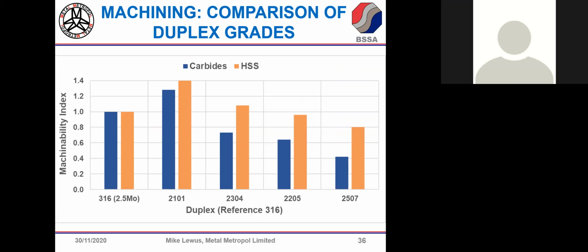More data on duplex, and pointing to the fact that we don't necessarily just have to stick with cemented carbides, which are probably the most widely used cutting tools. High-speed steel cutting tools are still used, particularly for intermittent cutting, and for troublesome materials like stainless steel, because high-speed steel is significantly tougher than carbides.